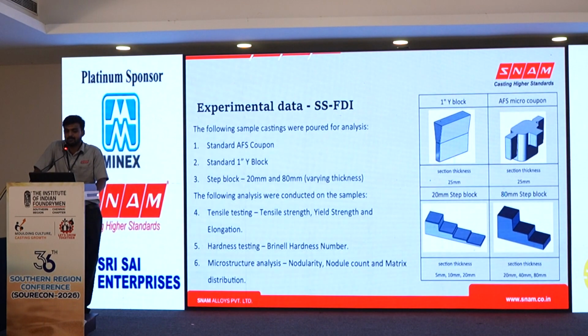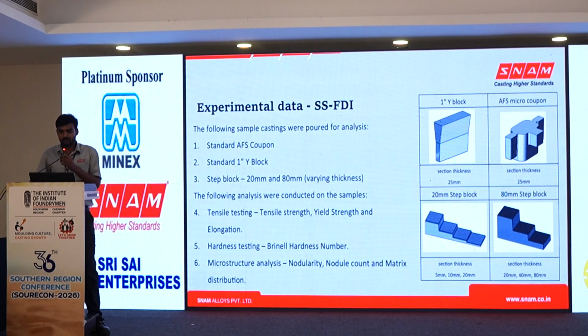So the following sample castings were poured during trials for mechanical analysis. We have poured standard AFS coupon to check hardness and microstructure of casting, and also 1 inch Y block to check the tensile properties, tensile strength, yield strength and elongation. And we have poured two different step blocks, 20 mm step block and 80 mm step block, which consist of 5 mm thickness, 10 mm thickness, 20 mm, 40 mm thickness and 80 mm thickness to check nodularity, nodule count and microstructure properties throughout the casting at different section thicknesses.